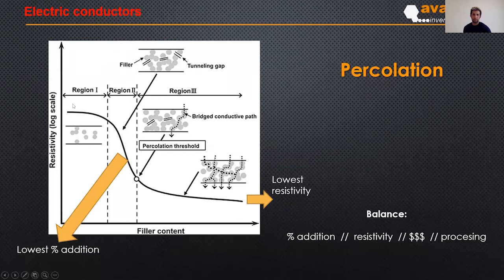At the beginning, when we are adding some black system or carbon black, for example, the connection between this carbon black is not real. There is no interaction between one part and the other. In this case, the material is insulating. Okay. There is a second region in which the conductivity changes drastically, because this is the point in which the conductivity of the system starts. Okay, in this point, the conductivity goes from insulating to conductive. The range of antistatic is more complicated.